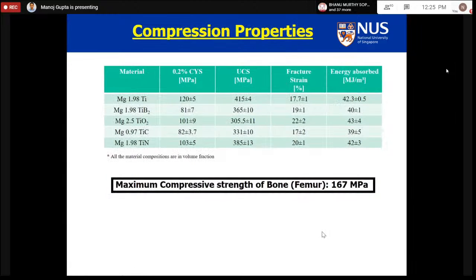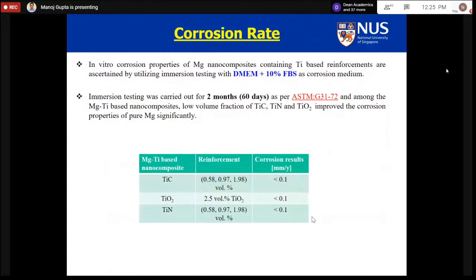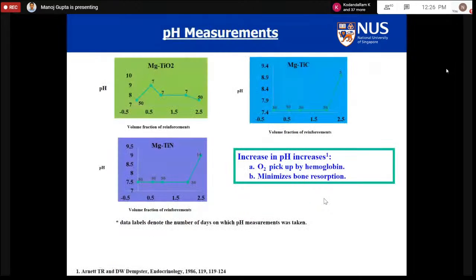Compressive properties again were superior to the compressive strength of the bone. You see, it's only 167 megapascal, but the maximum strength that these bioimplants can see is almost double that. So we did the corrosion rate because once a metal goes in the body, all the material that goes in the body has to go through the corrosion test so that they don't degrade. If they degrade also, the product should not be toxic. So based on the conversation with the surgeons, they need a corrosion rate of less than 0.2 millimeter per year, and all this material shows a corrosion rate of less than 0.1 millimeter per year, and they're taken to the next stage, which is the animal testing now.